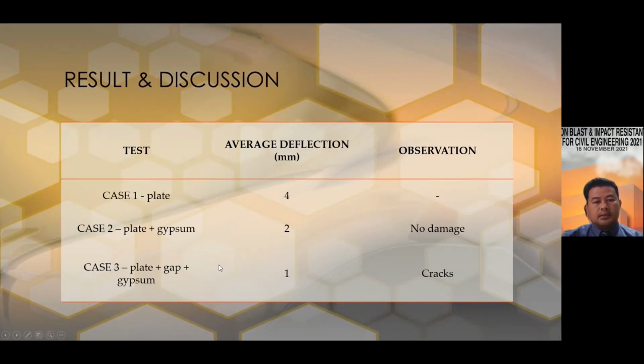This table shows the average of the results obtained from the field test. It can be seen that the gypsum board reduces the deflection of the steel plate when subjected to explosion, from 4 mm for case 1, steel plate only, to 2 mm when protected with gypsum board, and reduced to 1 mm if there is a gap between the plate and the gypsum board.